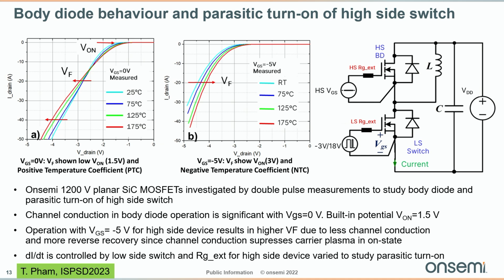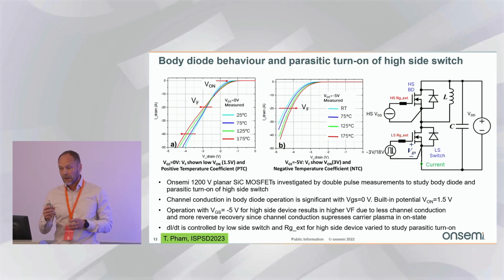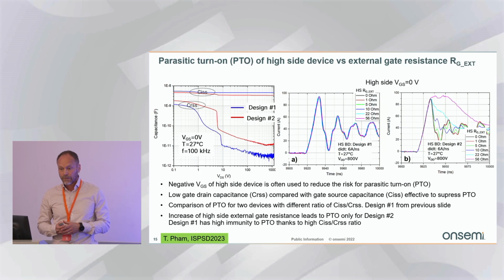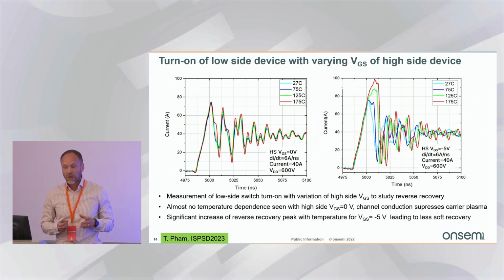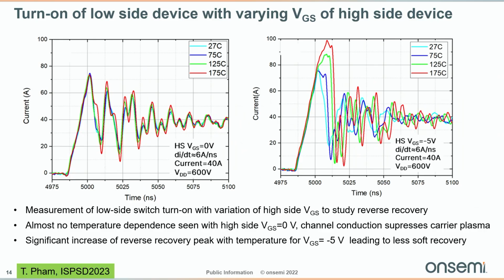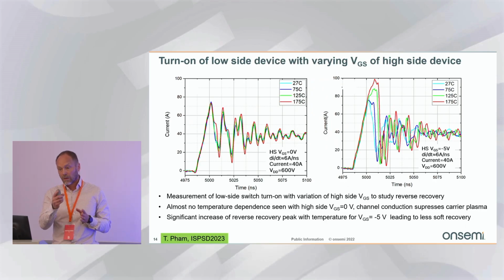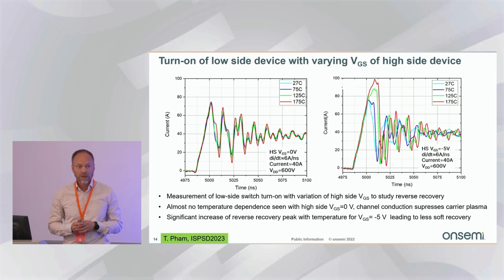So to the right, you see an experimental circuit for double pulse measurements where we have the low side switch, and we look at the high side body diode here. And in this measurement, we actually see the measured current for the low side device, but the peak you can see during turn on is due to the body diode capacitive current or carrier plasma, so the recovery. And to the left, you can see that even for a pretty high di/dt with VGS 0 volt, there is no temperature dependence for the peak current. So it's basically a unipolar operation. So a good recovery, although there are oscillations due to parasitics of the double pulse setup.